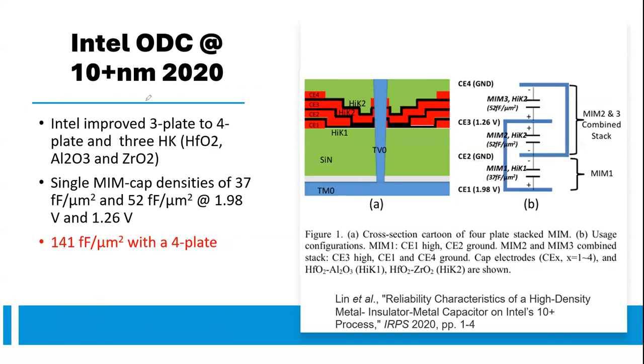And Intel ODC, 10 plus nanometer, they make it more complex now. There's a 4 capacitance layer, 4 layer, okay. They go from 3 plate to 4 plate, and then 3 high K: hafnium oxide, aluminum oxide, and zirconium oxide. They have more combinations of different high K. And they have a variety of MIM cap density, 37 to 52, and this is reasonably good. And the 4 plate one, they go to 141. Very decent, very decent. So the 52, 37, okay. So this is what they come up with. And they use a mixture, see that?